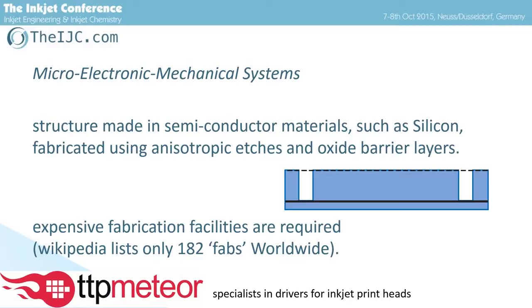So in my little diagram here, if this was part of a layer of silicon, a very thin, circular disc type thing, and maybe it has a layer in the middle of it of a dioxide perhaps, and you put a mask on the top with a couple of holes in it, and then etch with an anisotropic etch, so in a straight direct line rather than in all directions at equal speeds. It will cut straight downwards through that hole and keep going until it reaches something it can't cut. And then as long as you stop pretty quickly, you won't cut through that layer.